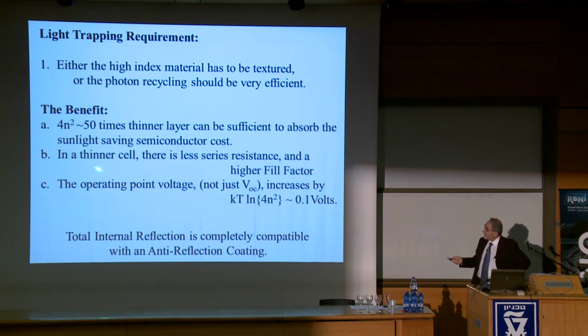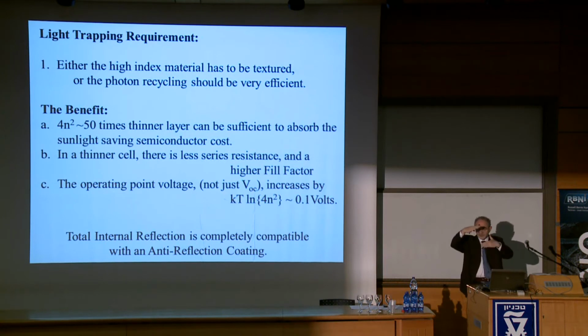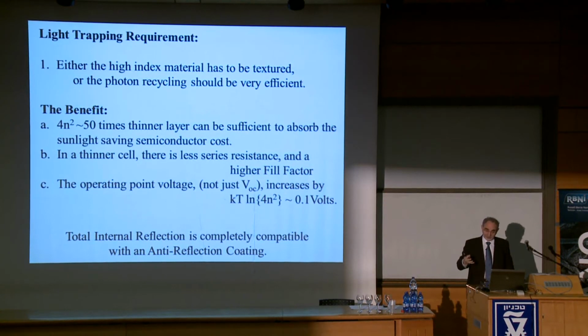Another advantage is that you can make the solar cell much thinner. There's less series resistance, and you could end up with this fill factor I talked about. You would be able to get the voltage and the current higher. And finally, this is a little bit more subtle. You have concentrated the sunlight into a thinner layer, 50 times thinner. Whenever you concentrate anything in statistical mechanics, the free energy goes up. A concentrated resource is more valuable. And so you get more voltage by kT log of 4n squared. And so you increase the voltage. This is natural log of 50, which is about 4. So you increase the voltage by about 1/10 of a volt.